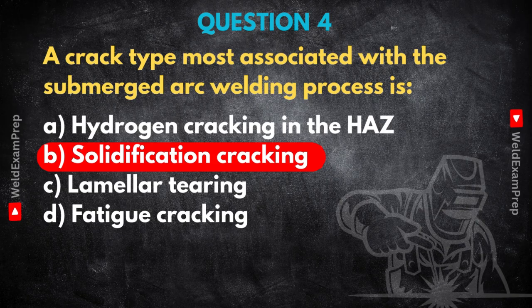Exactly. And because SAW has these large, deep pools that cool relatively slowly under the flux, there's just more time and opportunity for these impurities to segregate and for significant shrinkage stresses to build up across that mushy, half-solidified metal. That makes it more prone to this specific defect compared to many other processes. So as an inspector, if you know a component was made using SAW, does that automatically change your approach? Do you sort of put your solidification crack glasses on?